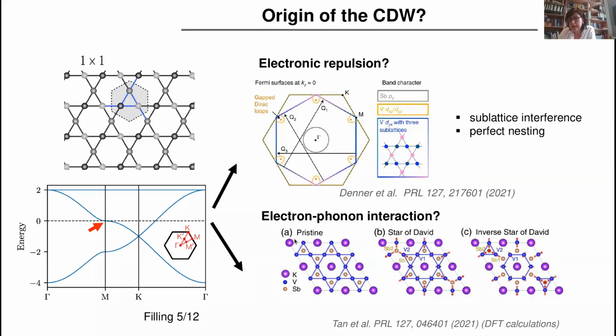There is also, of course, another interaction in these materials, which is the electron-phonon interaction, so that the electrons are coupled to the lattice, and there are some phonons. Here, what I'm showing is a phononic type of calculation done by Tan and collaborators, Bin Hayyan's group. Basically what they find, doing DFT calculations of phonon instabilities, is that the system, due to the phonons expected in these materials, will undergo a charge density wave of the kind that has been observed, Star of David or inverse Star of David.